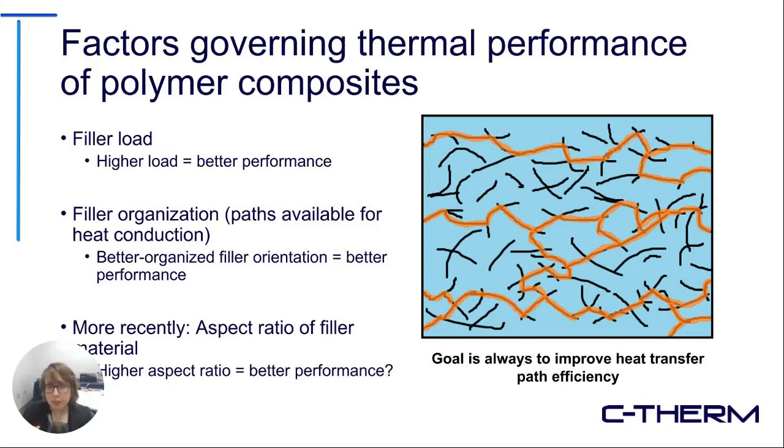But also, if your fillers are relatively more organized, if they're aligned in a single direction, for example, you're going to have more opportunity for that better performance because the end of one will be probably pretty close to the start of another one. And now, more recently, they've been looking into the effective aspect ratio.